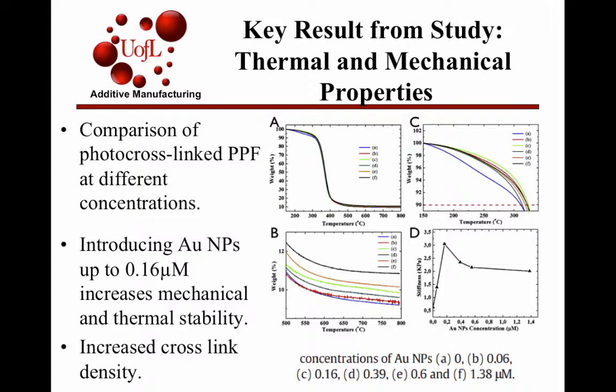They also looked at the mechanical and thermal properties. Graph A shows thermal properties, and B and C are zoomed in on different sections of graph A. As they varied the concentrations of the gold nanoparticles, each of the different colors is a different variation. All the different concentrations are listed below. You can see there's very little change in the thermal effects, which is what they were looking for. But they did say there was increased stability in the thermal properties. One of the big important things for them was chart D, looking at mechanical properties, and they said the properties started to degrade significantly after reaching the 0.16 concentration of nanoparticles. They said the peak was there because that was where the increased cross-linking occurred, and it started to degrade after that. So they recommended that as the optimum mixture to use.